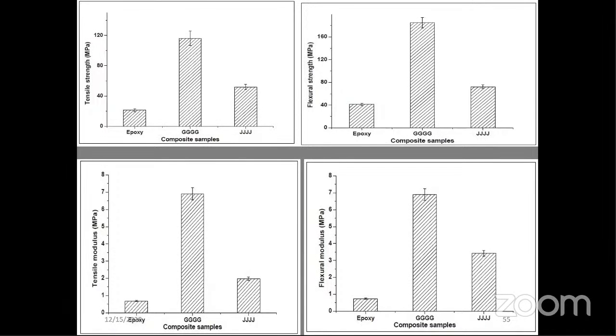to show the nanocomposite values, like these are my PhD results: epoxy, a pure polymer, with inserted glass fiber composites, the strength is increased. In the jute fiber comparison, the strength is not up to the mark for natural fiber replacement. This is almost only half of that material's strength. So we can't straight away replace the conventional materials with these natural jute materials. So that is compared with